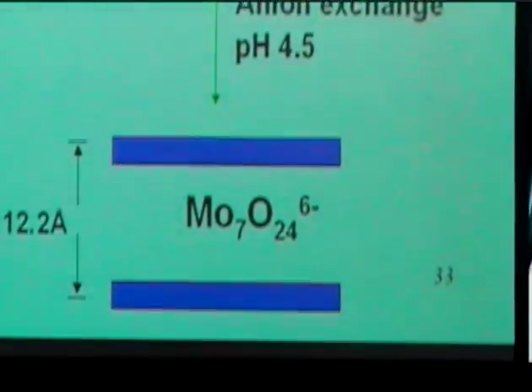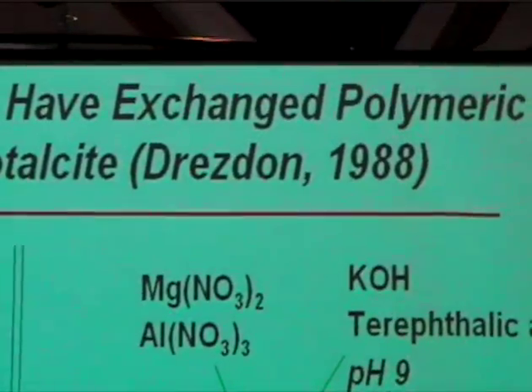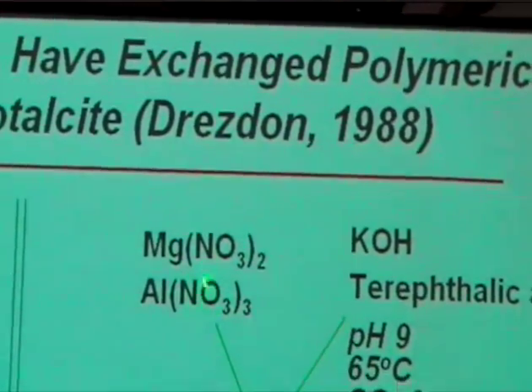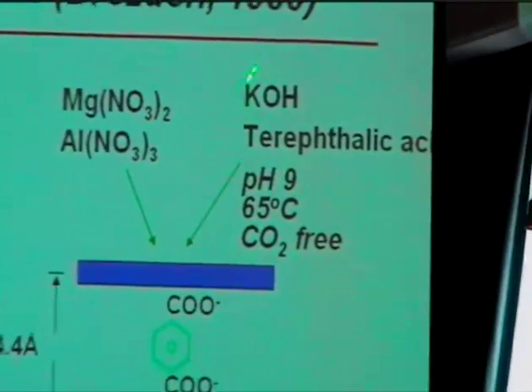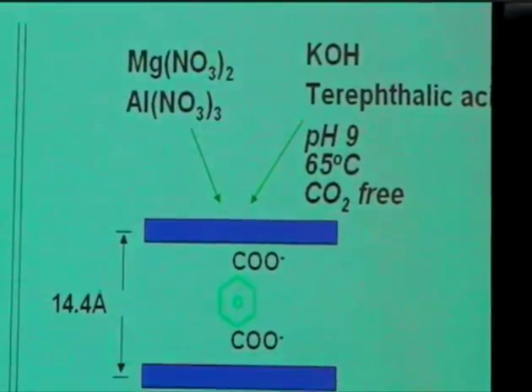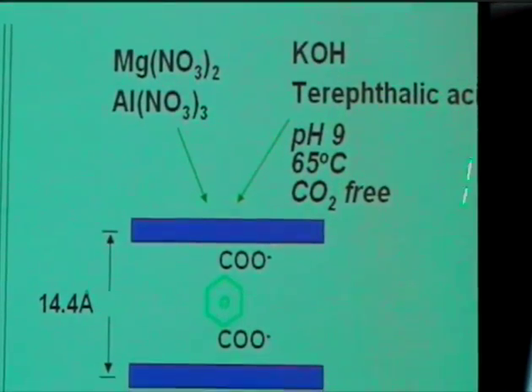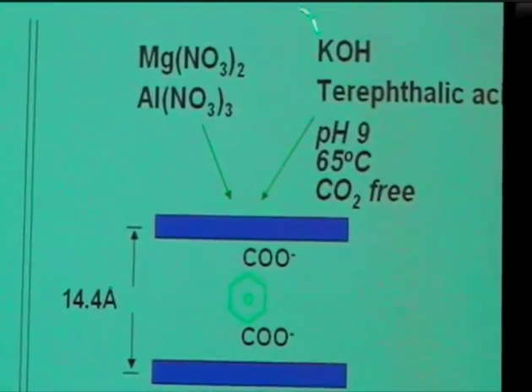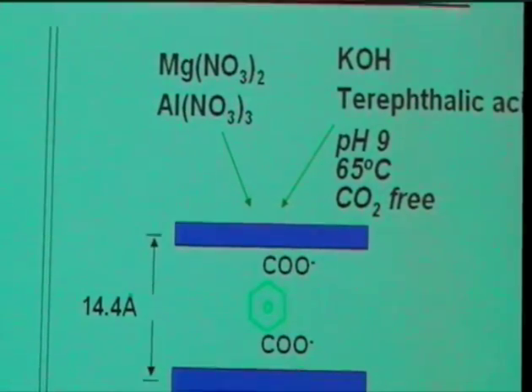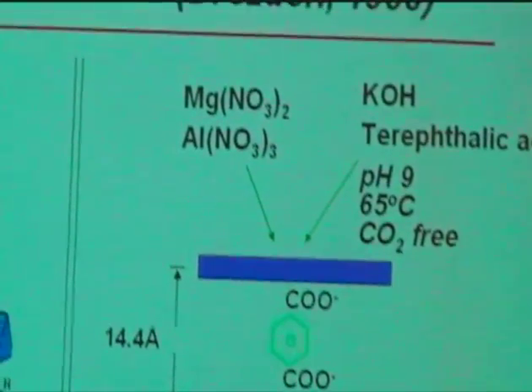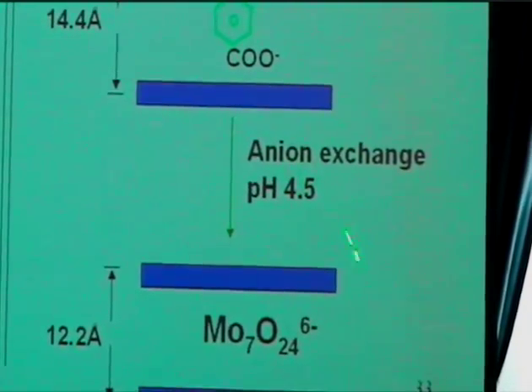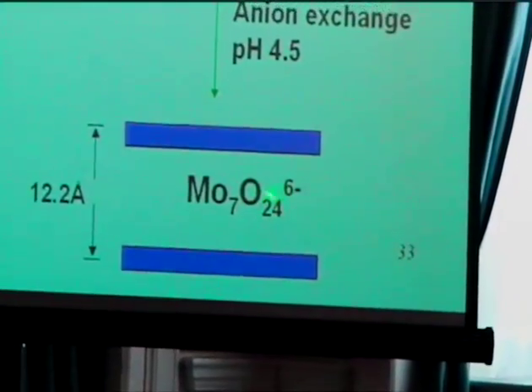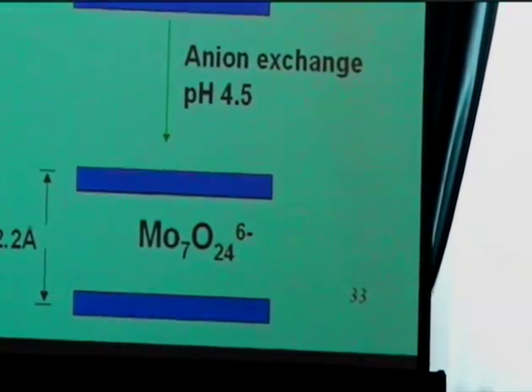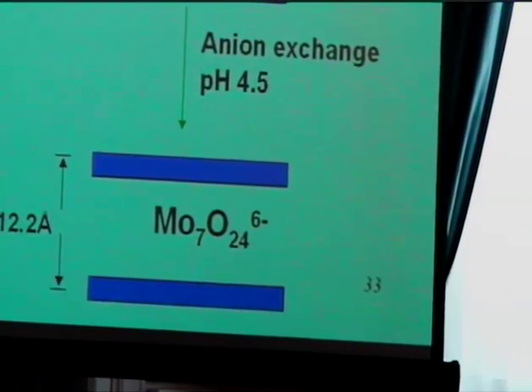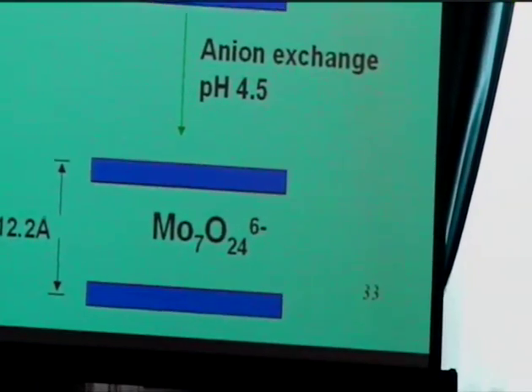There was a relatively recent report at that point in time by a researcher who was at Los Alamos at that time, and he found that if he did this precipitation of the magnesium and the aluminum in a base, but excluded carbonate, excluded CO2, and had terephthalic acid in there, he could get terephthalate incorporated here, and this would separate the layers and make a much larger distance than the 5 or 6 angstroms you get here. And then you could come back with an anion exchange with a polyoxo molybdate and get that incorporated. That was all we had seen with hydrotalcites and getting molybdenum incorporated into them. Okay, so that was kind of the background.